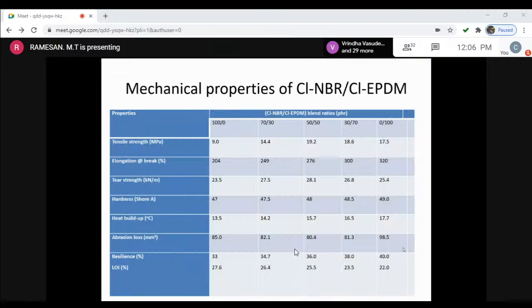These are some mechanical properties that we have studied in that system. And you can see that the maximum tensile strength is obtained for the 50-50 blend ratio. You know that the tensile strength of chlorinated NBR is only 9, whereas chlorinated EPDM is 17.5. And when we mix them together in that 50-50 ratio, the tensile strength is much higher than that of either of the individual systems.